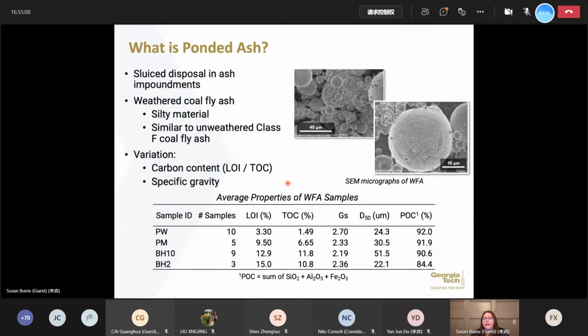So when we think about ponded fly ash, it's a little bit different. What we do with fly ash that comes out of the plant historically, if we can't dispose of it in a dry landfill, we will sluice it into an ash impoundment. And so this is generally a river that has been dammed, and we transport the ash hydraulically and let it gravity settle behind the dam. What this means is that these ashes weather over time. So they start as a silty material, particle size does not change, but what we'll see in the work that we've done is that these are similar to unweathered Class F coal fly ashes.